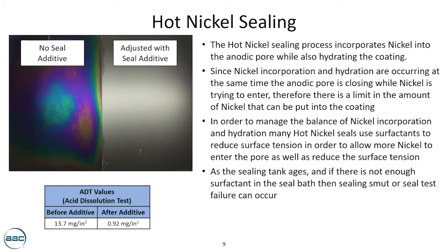So the battle with the hot nickel seal is twofold. One, you're trying to incorporate nickel into the coating, but also hydrate and pinch those pores shut. So imagine yourself trying to fill a pore with nickel with the pore itself shutting at the same time you're trying to do it. The issue with hot nickel and even mid-temp nickel is you're not able to optimize the amount of nickel that gets into the pore, and as a result, you could potentially not have as strong of a seal compared to other types of seal chemistry that do allow those two steps to occur in individual tanks. Now, the benefit of the surfactant is it reduces the surface tension and allows that nickel to go into the pore. But again, if that seal additive is not managed correctly, you won't get a good ADT.